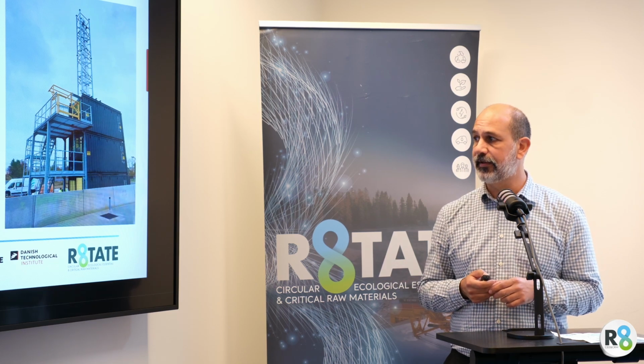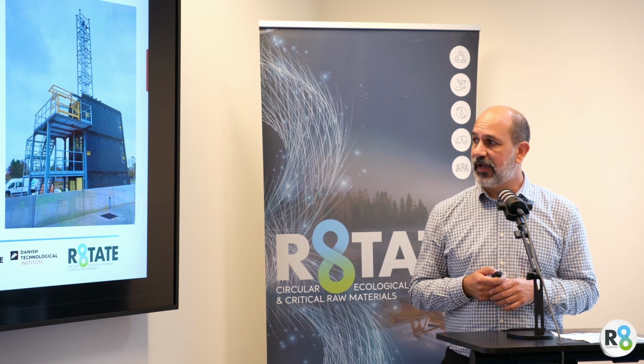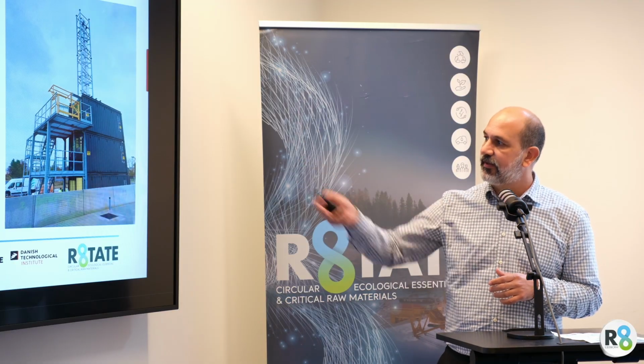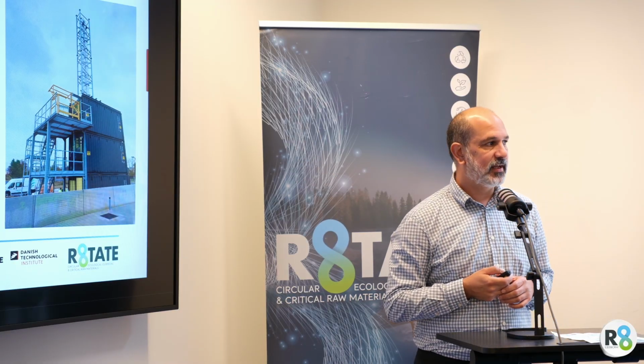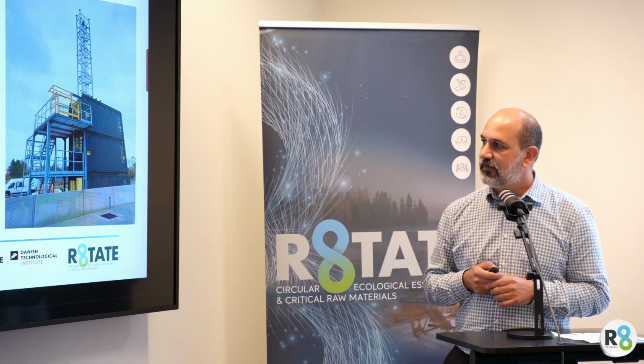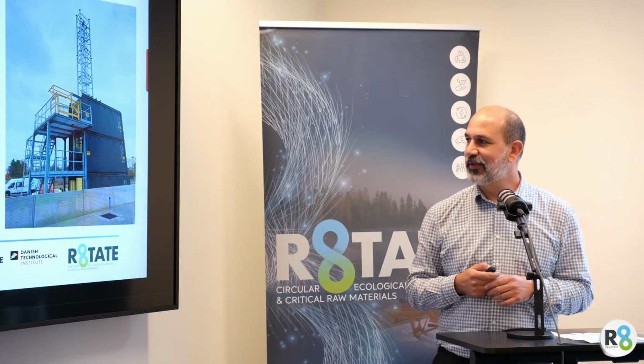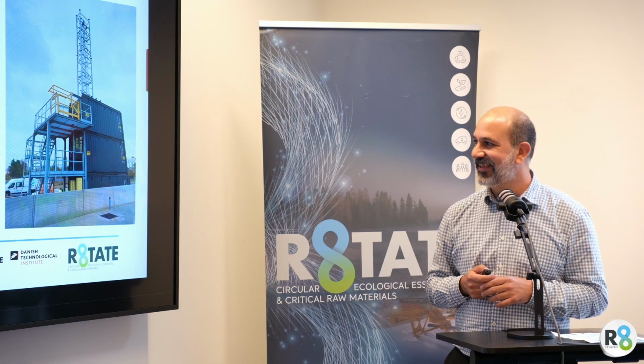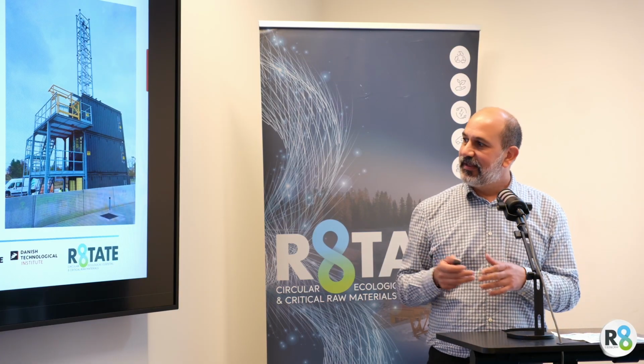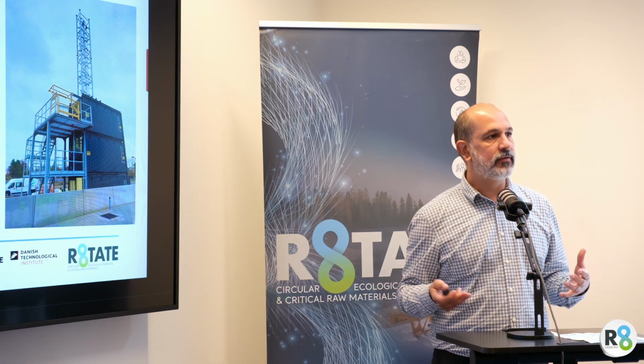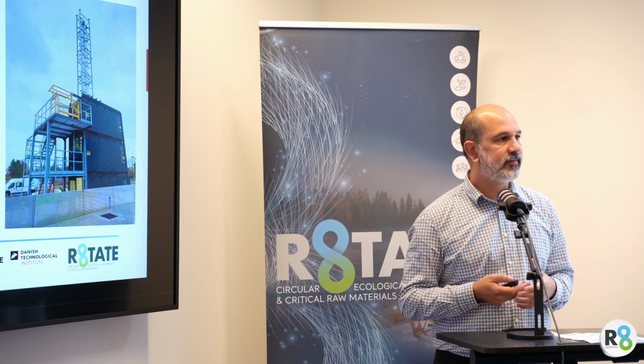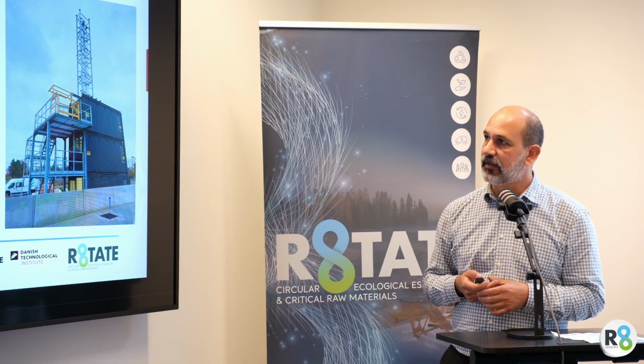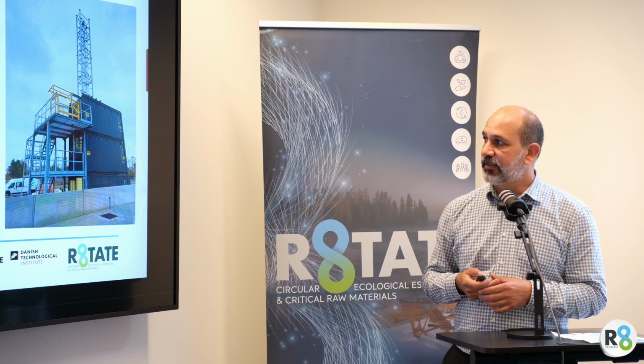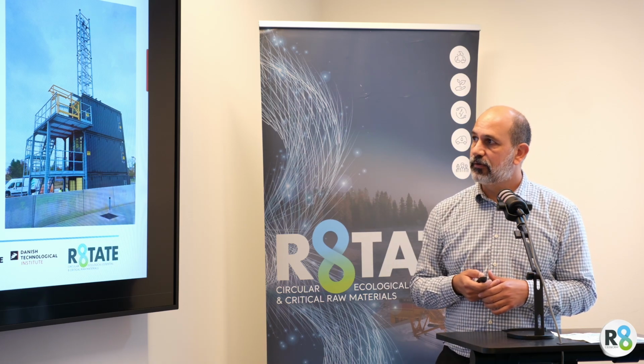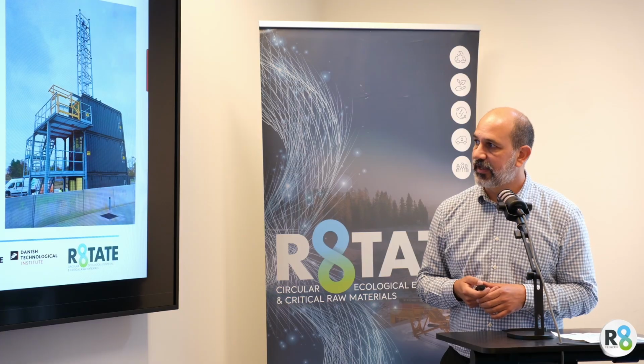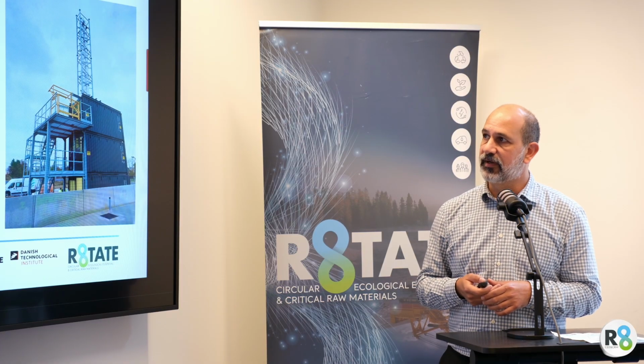So for this material, we also have a pilot plant with this new baby that we have at Vito, a flash calciner. It's a bit of a naughty baby because it's giving us a bit of issues at the moment. But we plan to execute this pilot and produce 1 ton of this material before the end of the Rotate project. So at the moment it's constructed and it's being commissioned, so we still need to do some tryouts before we can process the material at Rotate.